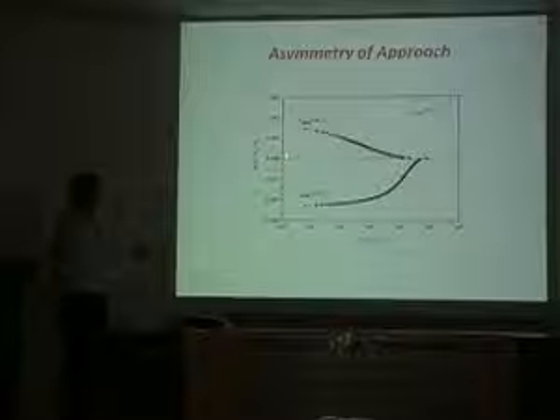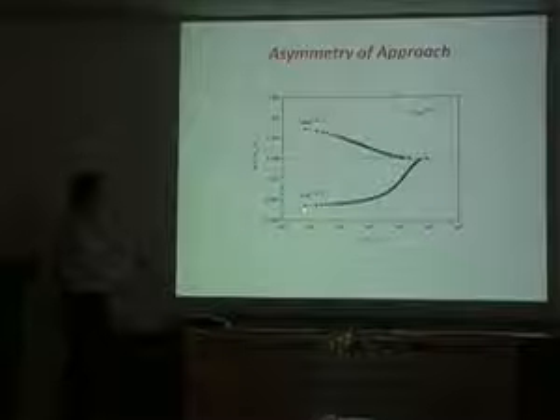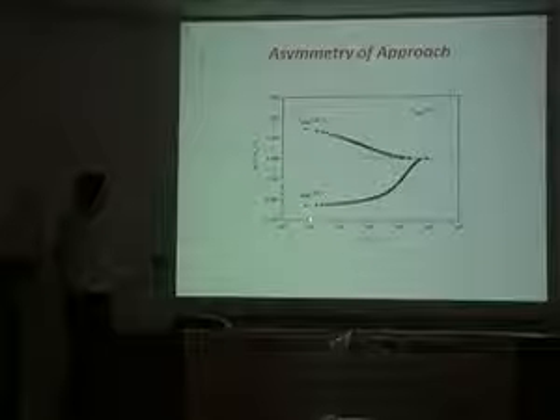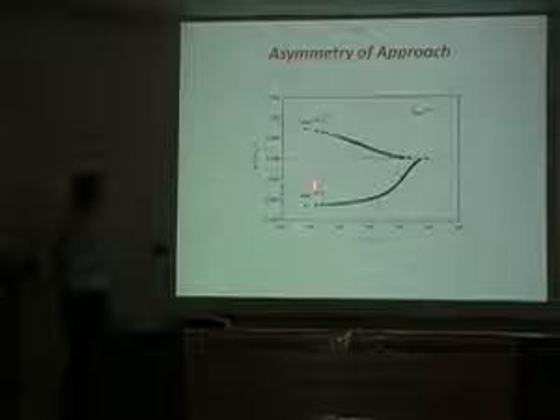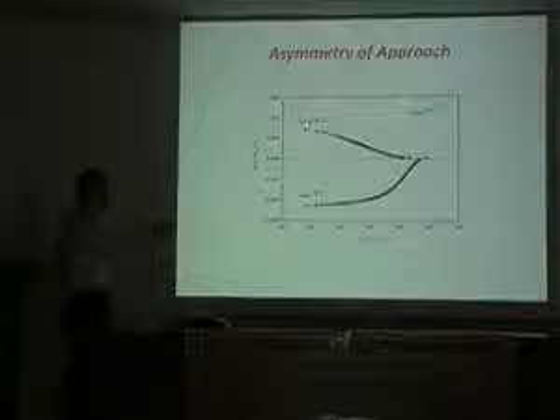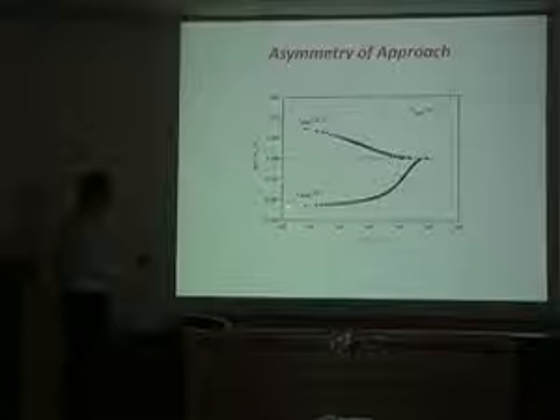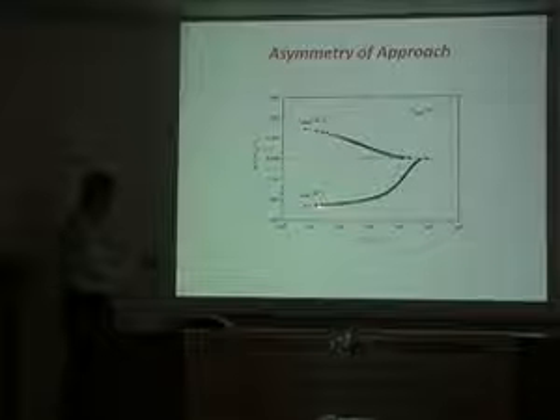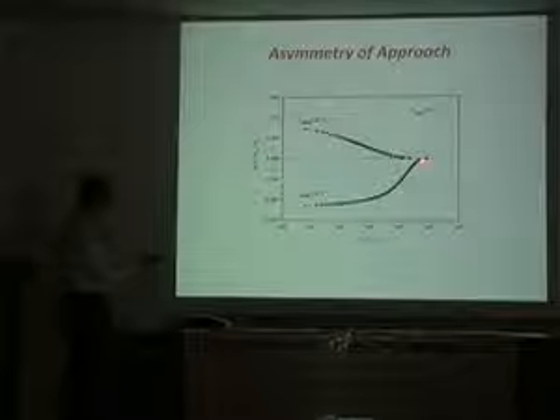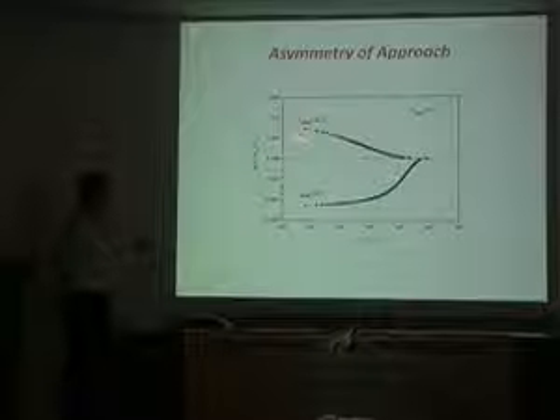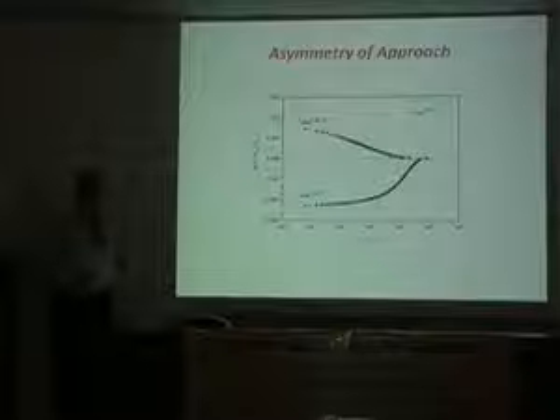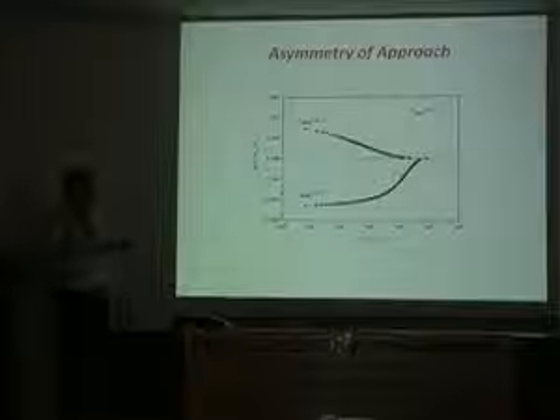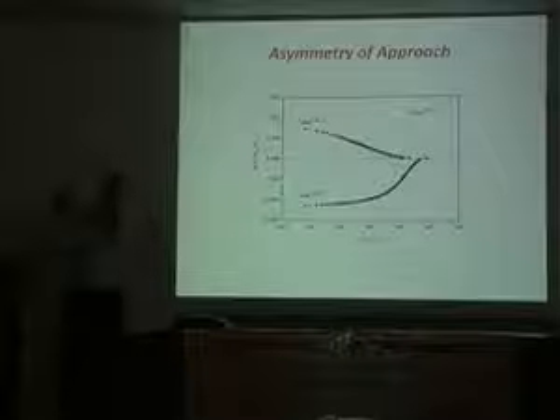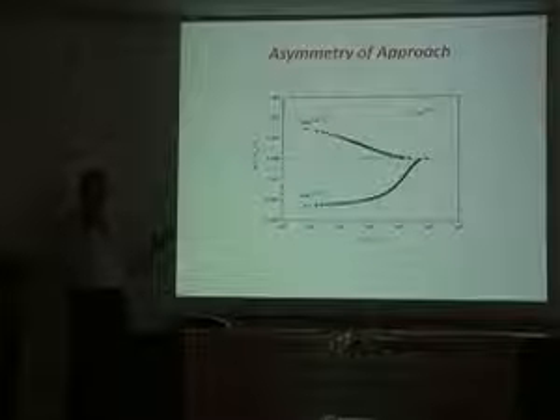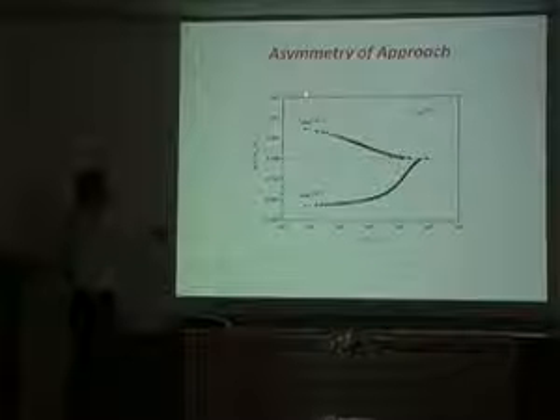And in the up jump, we see that it's quite different. By the time of just 10 seconds, we have a very big difference in the actual departure from equilibrium. And we find that this is coming along pretty slowly until it seems to catch up and then reaches equilibrium at a longer time than the down jump experiment. So what people think is happening here is that this is reflective, if you think in terms of free volume, of the material having a lot of space at high excess volume, so the molecules can rattle around and move.